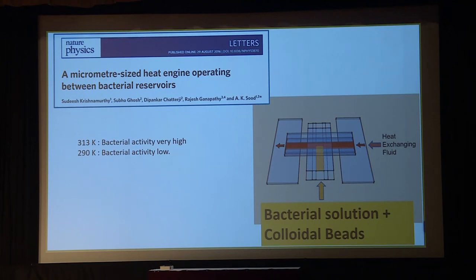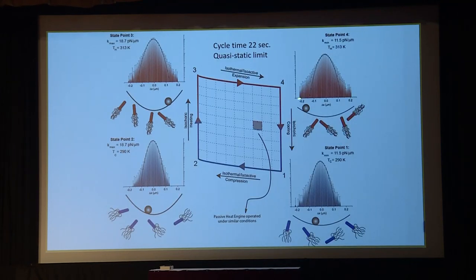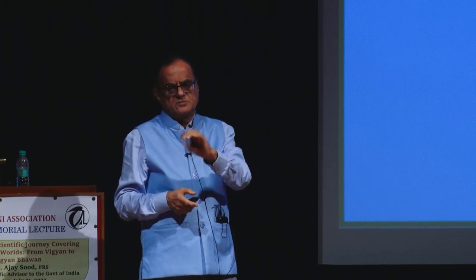I will not give you detail on these bacteria. This is something I touched upon in my last talk here, which was the beginning of these experiments. And what we showed was that indeed the probability distribution changes enormously when, instead of isothermal, we are doing isoactivity. High activity is like a high effective temperature. Then you have cooling of water, which means bacteria cool down. At low activity, then again heating. If the bacteria were not there, the engine would give you very, very small work, which I'll show you, and small efficiency.